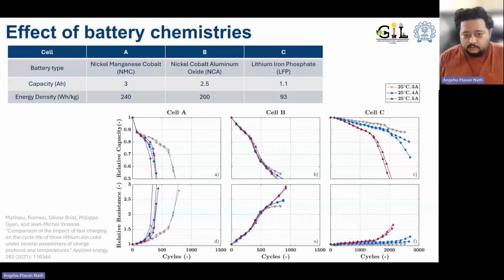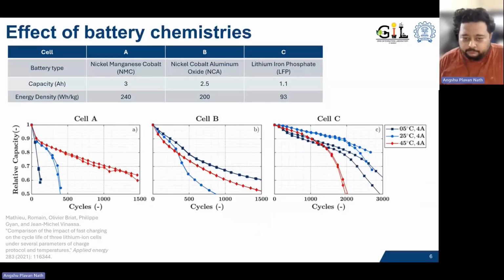But on the other hand, although cell C looks better in degradation, cell C also has very low energy density. If you see energy densities, cell C has around 93 watt-hour per kg, but cell A has 240 watt-hour per kg. Now, depending on use case, we may want to use different battery chemistry as per requirement.